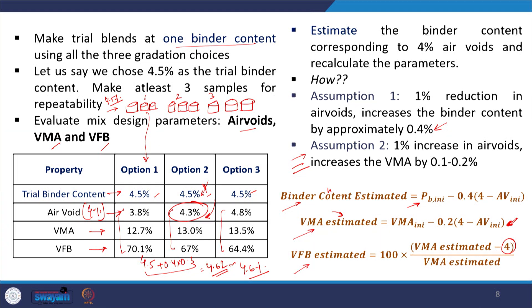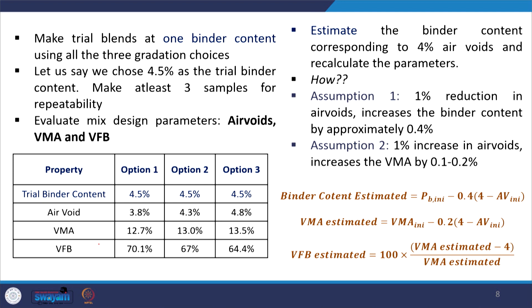Taking another example for VMA: using the assumption that 1 percent increase in air void increases the VMA by approximately 0.2 percent, if we look at option 3 — at 4.8 percent air void, the VMA is 13.5 percent. To find VMA at 4 percent air void, we calculate: 13.5 minus 0.2 times 0.8, giving approximately 13.3 percent. Similarly, VMA can be estimated for other options, and once we have the estimated binder content and VMA, VFB can also be calculated using the simple equation shown.